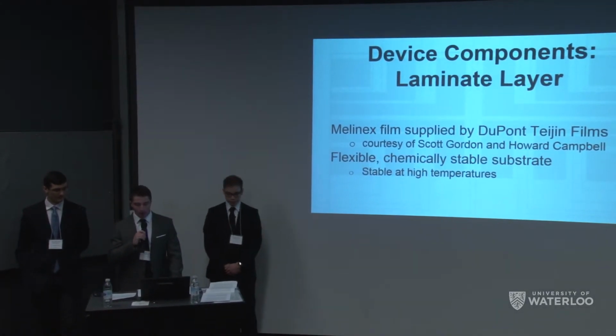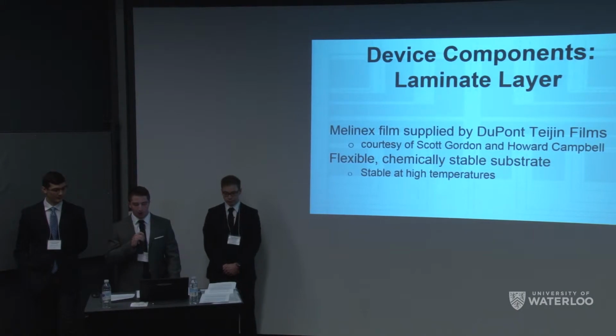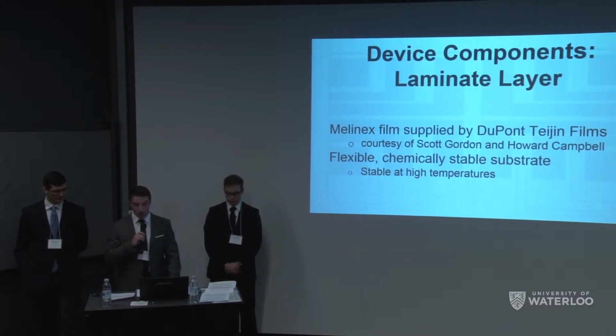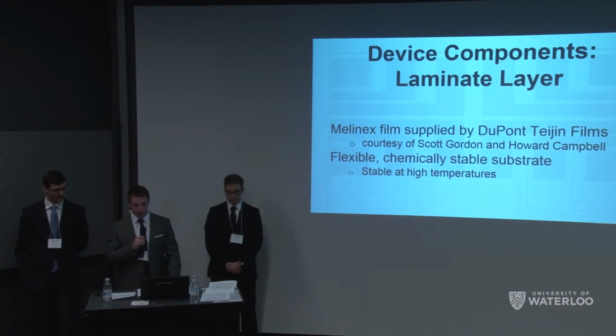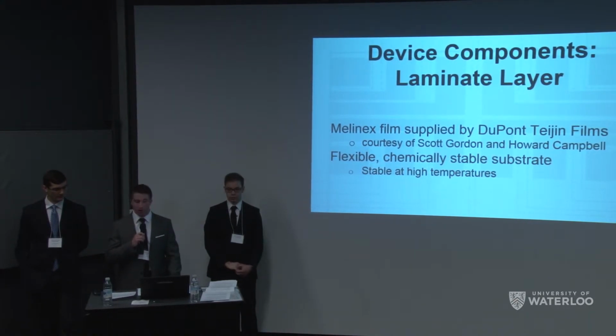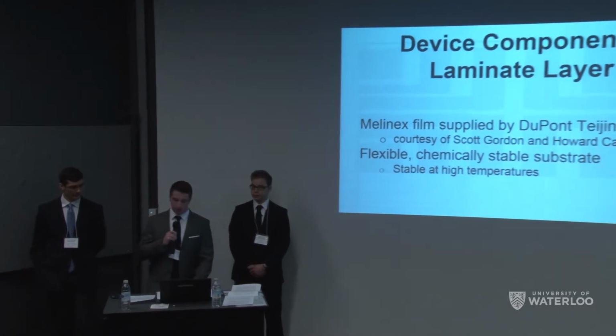Our laminate layer was chosen with a little bit of help from our friends Howard Campbell and Scott Gordon at DuPont and DuPont Teijin Films. DuPont sent us some samples of a plastic called Melinex to mount our silver nanowire electrodes onto. Melinex films are flexible and chemically stable substrates made of polyethylene naphthalate. The films even tolerate more than enough heat to allow us to thermally treat our silver nanowires right on top of them, making the Melinex films ideal for large-scale manufacturing.